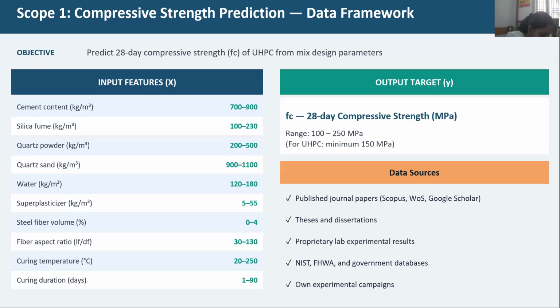So from the collection of the literature data set, we can do the prediction of the compressive strength either at 28 days or even at early days, let's say 7 days, 14 days, 28 days, or in the later days, such as 56 days also, particularly if you are using fly ash as one of the supplementary cementitious materials. So this is one scope with respect to compressive strength prediction.